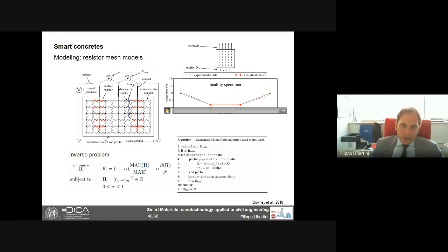If you look at the video on the top right, you see that we have a specimen with different pairs of electrodes. We measure the voltage drop across all the sections, and we compare the analytical model in red, so the resistor mesh after calibration, with the experiments. So you see that after calibration, we have a good match.